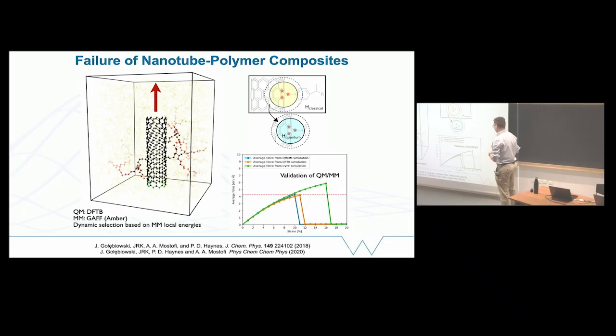And you can validate this at a high level by looking at something like the stress-strain curve. So we apply a strain, and we see how hard we have to pull before the thing breaks. The full calculation can be done as a one-off in orange, and the very much cheaper QM/MM-style calculation in blue gives pretty much the same failure strain. Whereas if you use only the classical model, similar to the brittle fracture examples that I showed you, you end up pulling much, much harder before any bonds break, because those classical models are not really designed for fracturing or breaking covalent bonds.